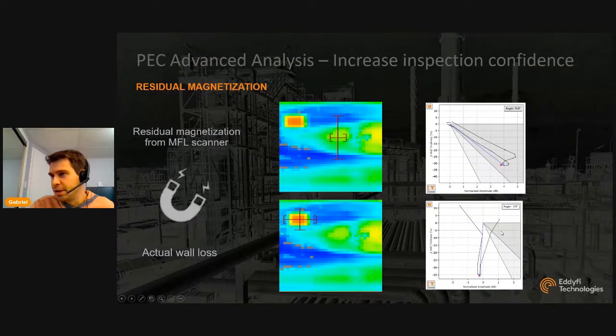Residual magnetization on, this is a plate that was scanned by an MFL floor scanner. Basically, it's leaving very strong residual magnetization, 30 Gauss measured at the surface of the component, but the PEC tool identifies those areas of magnetization as a false positive. We've got here a defect that's actual wall loss, and here the tool again is going to identify that as a real indication.